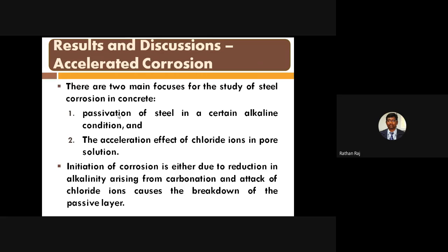Now, when we come to the accelerated corrosion setup, there are two main focuses for the study of steel corrosion. One is passivation of the steel in a certain alkaline condition. The other one is the acceleration effect of chloride ions in the pore solution. So initiation of the corrosion is due to the reduction in the alkalinity. That is the very first point, because at a later stage, after 10 years or after 15 years, because of the reduction of the alkalinity, the corrosion starts. Carbonation starts, and it leads to the corrosion.